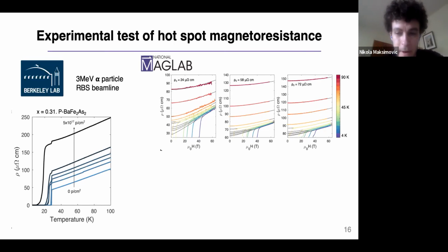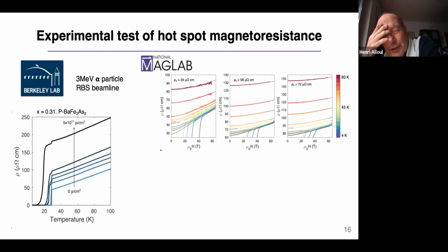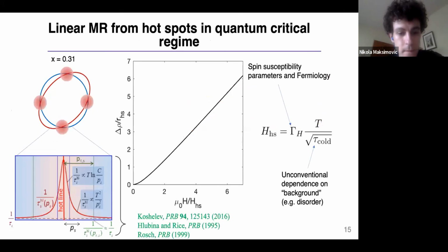You're correct. We have done very careful work on the cobalt 122 with Florence Rullier-Albenque, in which we tried to analyze the transport in terms of two bands and two different scattering rates, showing that they were very similar. In that case, we find a T-squared term and not even a T-linear one. Here, all this is done as if it is a single band. In your work, were you looking primarily at the temperature-dependent resistivity?